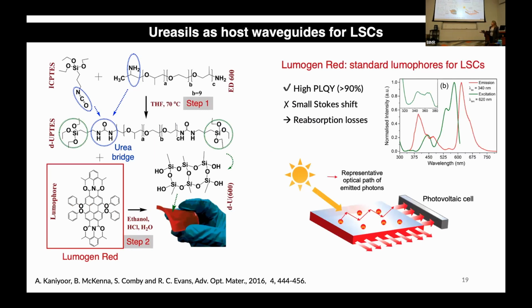So this is Lumigen Red. It's a perylene dye, and it's the archetypal dye used in LSCs because it has a really high photoluminescence quantum yield of 90-odd%. But the problem is it has a really small Stokes shift, so a small separation between the absorption and the emission spectrum. You see this strong overlap here, and this is a problem because it leads to reabsorption losses as photons are emitted and transported via total internal reflection through the slab to the edges.